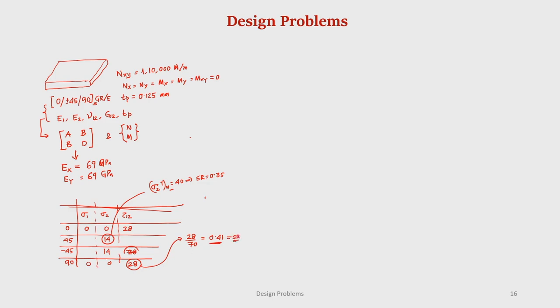Maximum strength ratio is at this. But you can see that this is 0.4, which means it is far away from failure, no ply will fail under this. Therefore, what that implies is that we can still reduce the number of plies, or because the strength ratio is very low, we can actually go for a glass epoxy laminate and check with that.